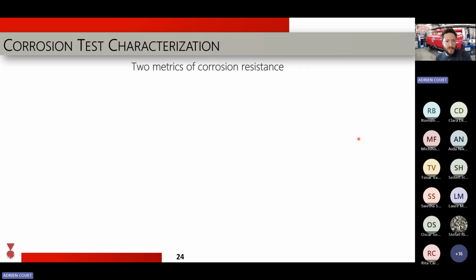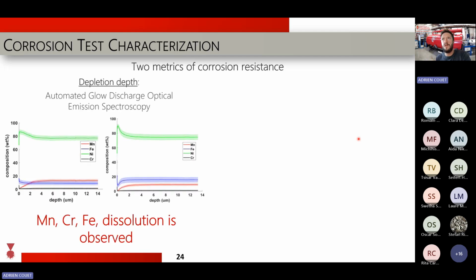So we use two different metrics of corrosion resistance. How do you characterize corrosion resistance? We used what's called glow discharge optical emission spectroscopy. We have one in the lab that allows us to really obtain depletion depths. On the left here is your surface, and then you can get the concentration as a function of depth using this method. It's a very quick and powerful method to get very accurate values of your elements. And you see the depletion, for instance, of manganese for this alloy here, and you see the depletion of iron and manganese for this alloy here.